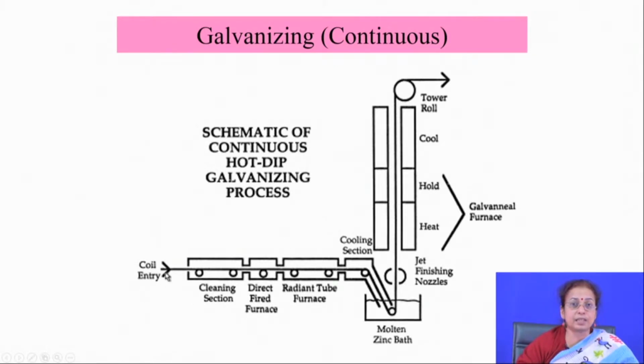In the cleaning section, you clean by different techniques like solvent cleaning, pickling or drying, and then you can go for fluxing, and then hot dipping. Finally, by jet finishing nozzle you go on finishing and monitor the thickness, and then you can go for the galvannealing operation in the furnace. So this is the hot dip galvanizing process, the continuous processing.